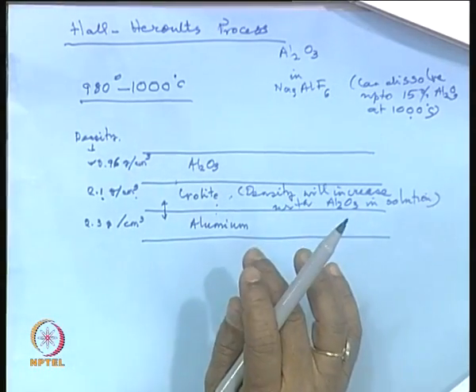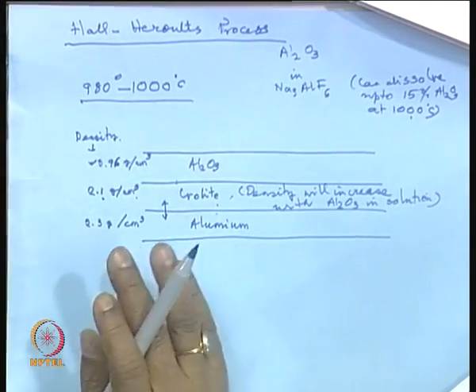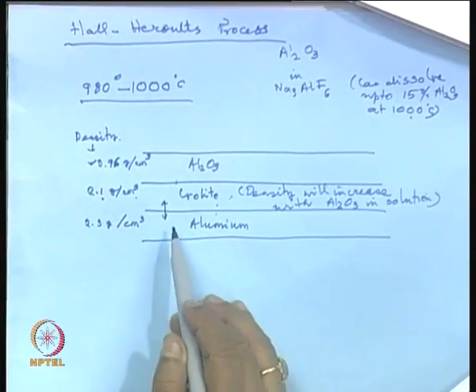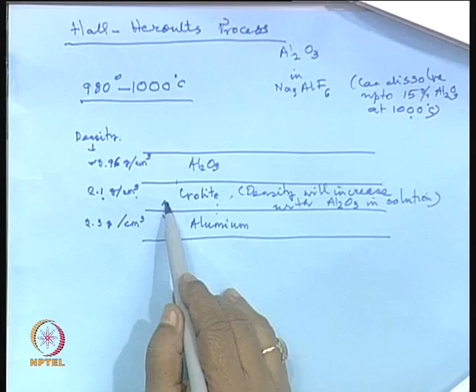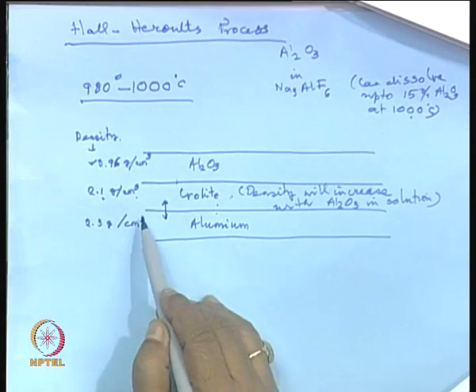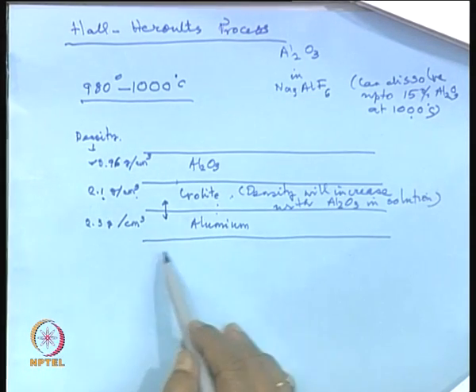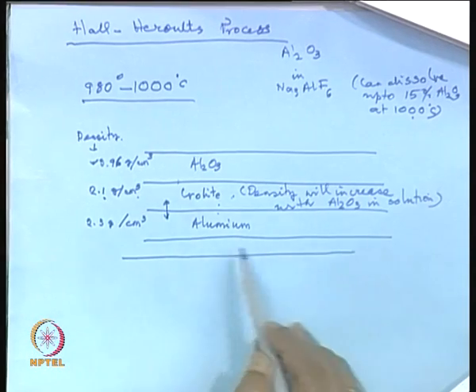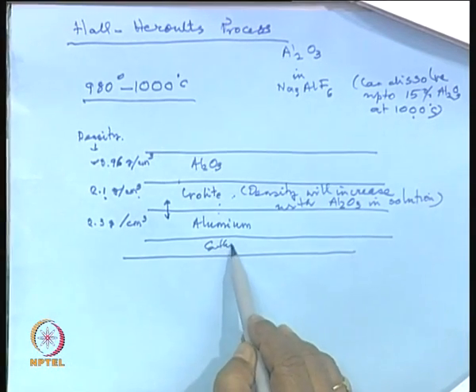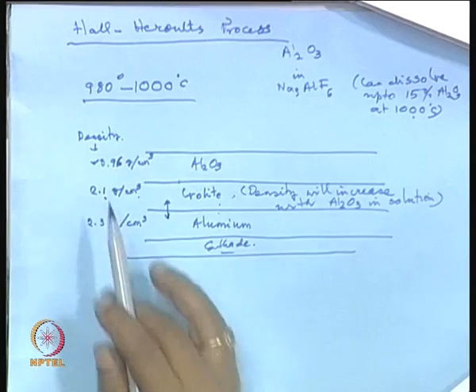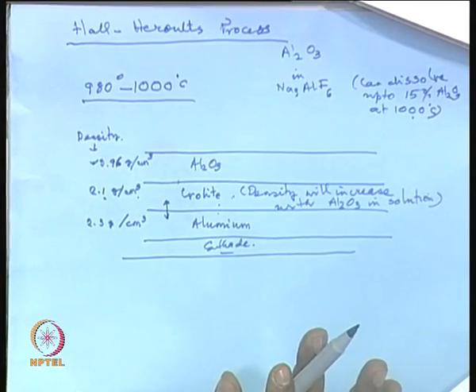Temperature will be 980 to 1000 degrees centigrade, say 5, 6, 8% alumina, and then we have a separation between cryolite and aluminum. Aluminum stays at the bottom above the graphite cathode. It is also protected from everywhere, so that there is no question of its getting oxidized. This is the basic scheme.